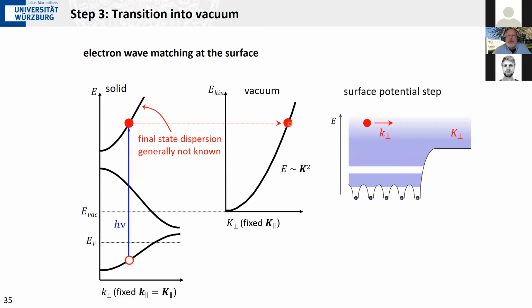It has now this energy at this particular K perp, capital K perp, in the vacuum, and you see that capital K perp does not have to be the same as small K perpendicular. But what we measure at our detector is this value of K perp, capital K perp. So how can we get information about small K perp from this? Well, there are 2 ways. Either you know what the band structure here at these photoelectron final states is, and that's typically not the case.